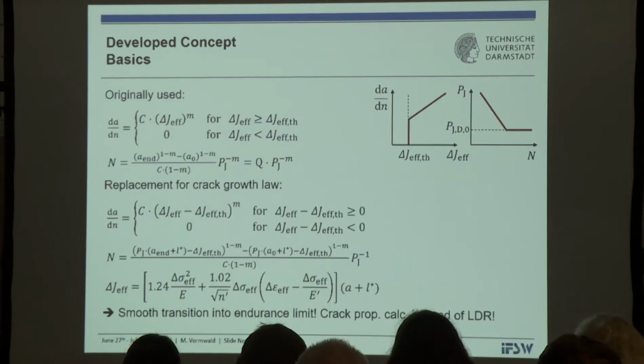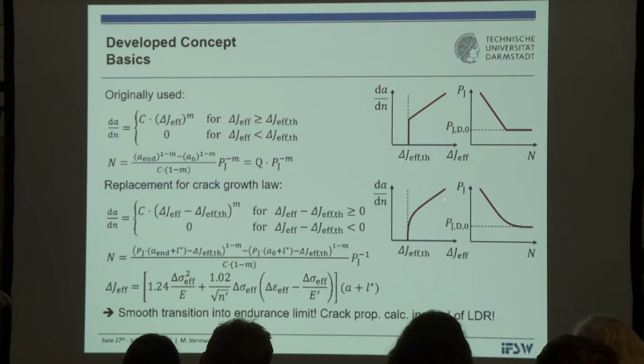So we developed new models, which were introduced in such a way that we now perform real crack growth integrations cycle by cycle and no longer damage accumulation. When doing so, we could modify our crack growth law from the simple power law to a law which also includes the threshold in the crack growth rate calculation. And this has some advantages because we no longer have this knee point in our crack growth rate equation, but we have a smooth transition from the linear Paris regime into the threshold. And this means that our constant amplitude damage parameter life curves do not have a knee point, but a smooth rounding into the endurance limit.